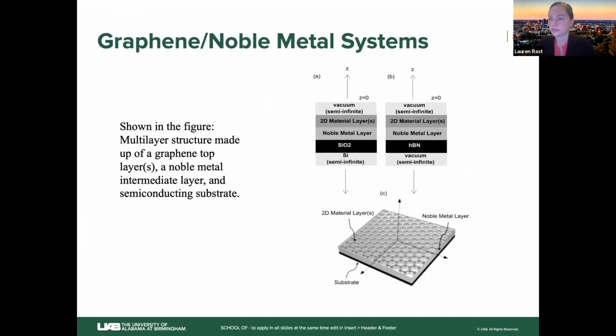Okay, so in this type of structure, I'm going to show the spectral results for this type of system, adding different layers of 2D materials, starting with graphene. We have a multi-layer structure with graphene top layers, various numbers of layers, some intermediate layer made out of a noble metal, and then a semiconducting substrate below. So we'll look at silicon dioxide and also hexagonal boron nitride spectra.